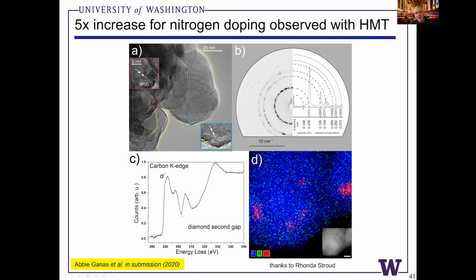But this is the EEL spectrum of the diamond. You can see this characteristic second gap in the electronic density of states. And then this is an EDAX map of nitrogen, argon, and also carbon in the diamond materials. You can see little points of argon emission, little point defects.